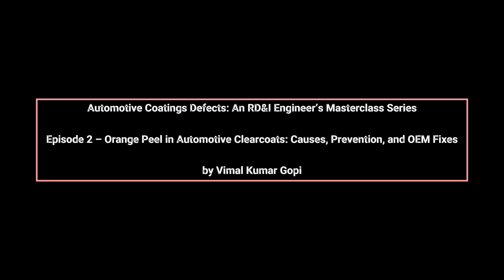OEM troubleshooting begins with surface observation under controlled lighting to distinguish orange peel from related defects like stippling, poor leveling, or overspray roughness. Reflection tunnels or side lighting highlight the characteristic dimple pattern and help quantify severity. Once confirmed, the corrective path is multi-pronged.